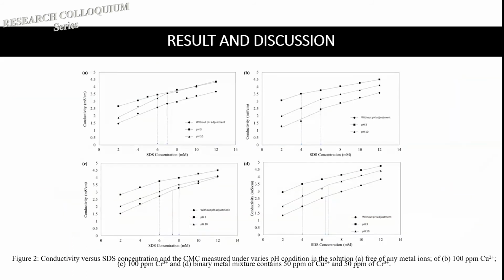Alright, so now these are the results that we obtained from the first section to determine the CMC. I would like to draw your attention to the first graph. This is conductivity versus SDS concentration, free of any metal ions, so this is just the CMC that we measured in water only. You may realize that when we increase the SDS concentration, conductivity increases. This is because we are adding more SDS molecules, which are ions. These ions are free moving, so they contribute to the increment of the conductivity.